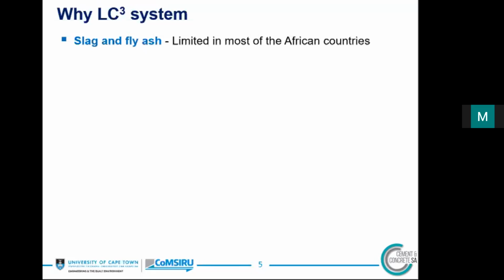Now, due to the increasing pressure to reduce environmental emissions, in the long term, the availability of fly ash is also in doubt. Also, the Saldanha Steel Plant in the Western Cape ceased to operate in 2020, meaning that there is no longer slag in that region. So in this case, it is important that we start to think about alternative materials before it's too late.